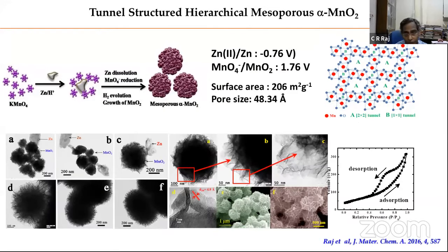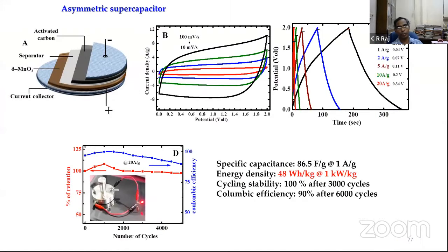Okay, this is another one. What we have here is the same MnO4 minus. Again, this is an accidental discovery, playing with the redox potential, right? So you will be able to appreciate the redox potential that is listed. You look at the potential, you play with the potential, and then come to a material, and use that material for the fabrication of your asymmetric supercapacitor. So this is a device that we have fabricated. And at the end, you are able to have a device. Yeah, this is a demonstration level, and you have your specific capacitance and energy density, and your Coulombic efficiency of 90% after 6,000 cycles. That is phenomenal for this material.